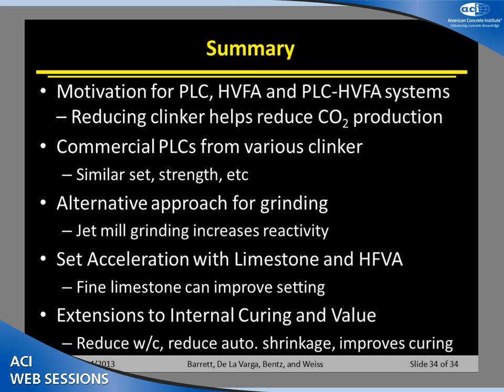Internal curing, how are we going to achieve that in our regular mixtures? Are we going to do that with lightweight fine aggregate, or can we also do this internal curing through lightweight coarse aggregate? Well, conceptually, you can use fine aggregate or you can use coarse aggregate. I would advocate using the fine aggregate because it's better distributed throughout the mixture.